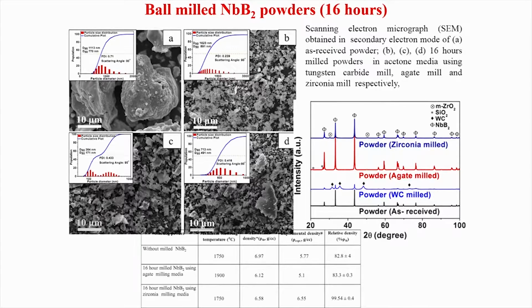Now, niobium boride is one of the members of the transition metal borides, and the consolidation of transition metal borides like titanium diboride and zirconium diboride faces similar challenges for niobium boride. So, the first thing is to start with the starting powders. In the top panel, figure A is the unmilled powder, and B, C, D are after ball milling for 16 hours with tungsten carbide, agate, and zirconia respectively.